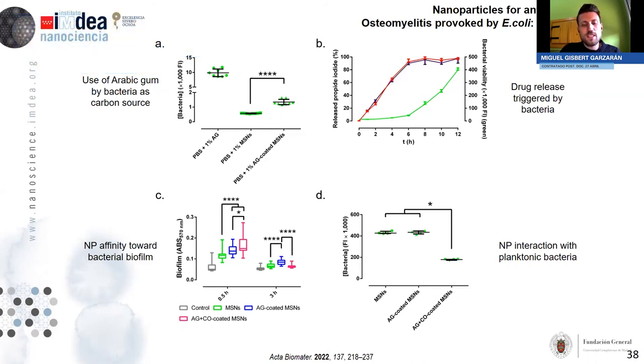However, it's quite hard to administer nanoparticles intravenously and then expect that they will accumulate in an affected area because we don't have the same physiological features. So in this sense, and for the case of osteomyelitis, for instance, it is very interesting if we administer the nanoparticles locally via an injection in infected bone. So if we have something on the surface that will attach to the bacterial biofilm, this means that if we add our nanoparticles into the bone, those nanoparticles will remain in the infected area because they will attach to the bacterial biofilm. In other words, we will get a high concentration of our nanoparticles because they won't leave the infected area. And this is good because if they remain in the infected area, they can exert the antibacterial effect.